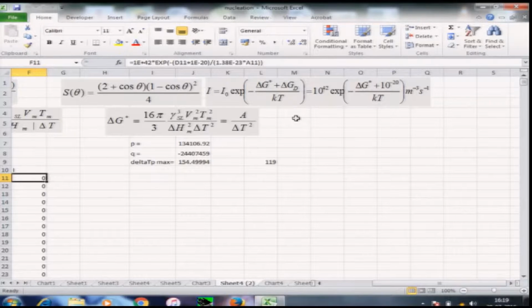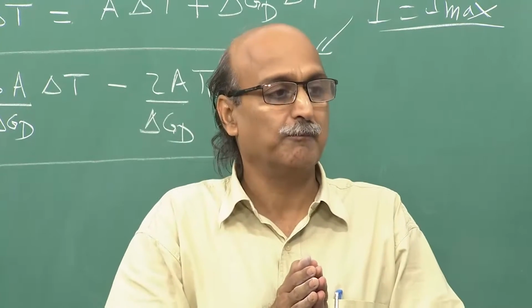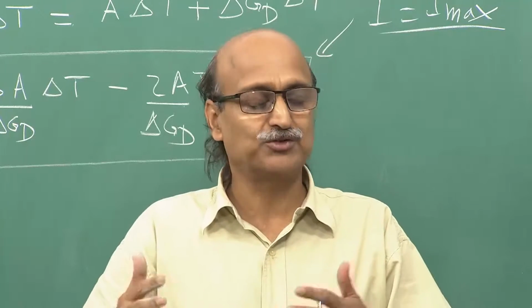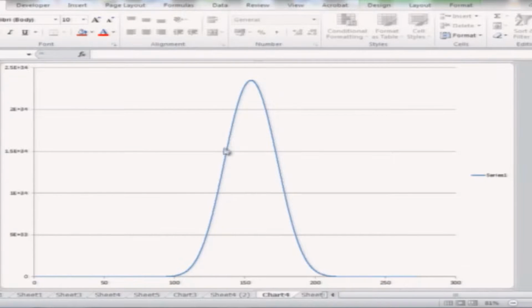So, the probability of the successful jump goes down. So, the number of critical nuclei becoming supercritical starts to drop. So, there is a trade off. As the temperature goes down, the mobility of the atoms goes down, but the driving force for the nucleation is increasing. So, these two opposing forces initially lead to an increase in the nucleation rate, it goes to a peak, and then it starts to drop again.